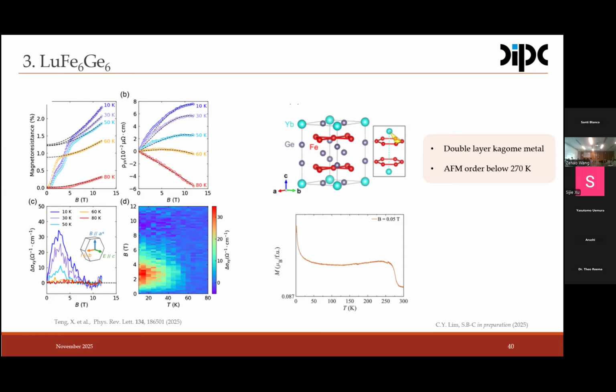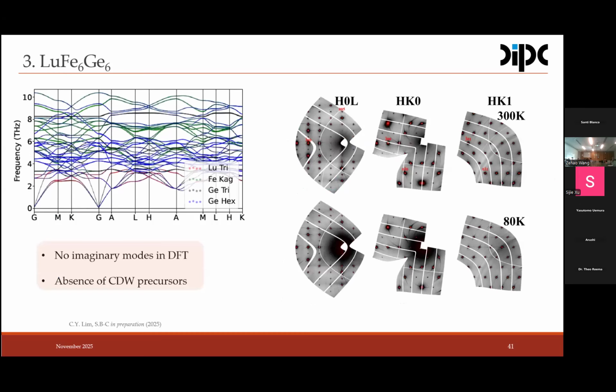It has an antiferromagnetic transition around 270 Kelvin, and the spin configuration is the same as iron germanium. Spins are out of plane. It's an A-type antiferromagnetic material. If we look at the phonon spectrum, all phonons are positive. We don't expect any charge order, any charge density wave, or any new periodic lattice distortion, which indeed we confirmed by the diffuse scattering experiments. At high and low temperature, the diffraction pattern is more or less the same. The sample is good. As you can see, Bragg peaks are pretty sharp, despite this being a diffuse signal.